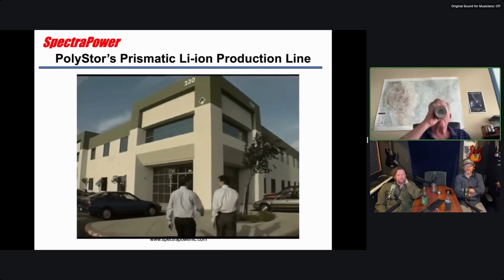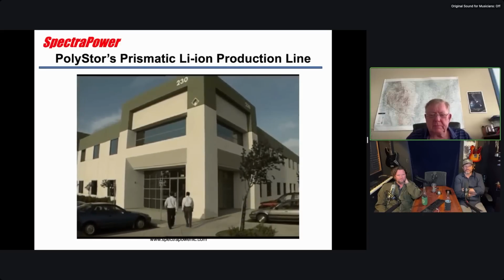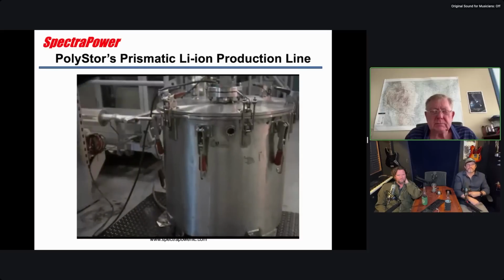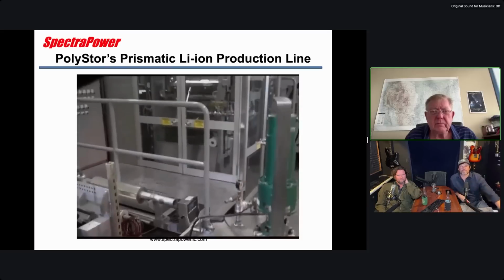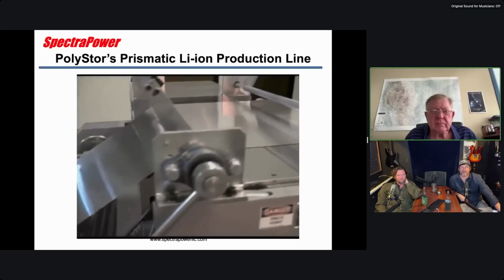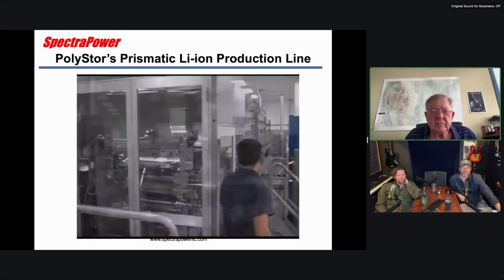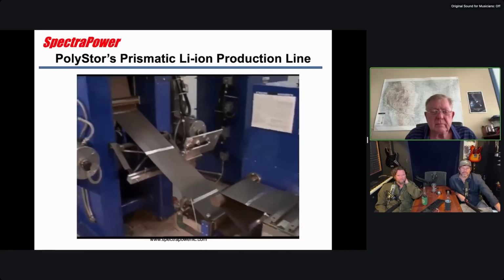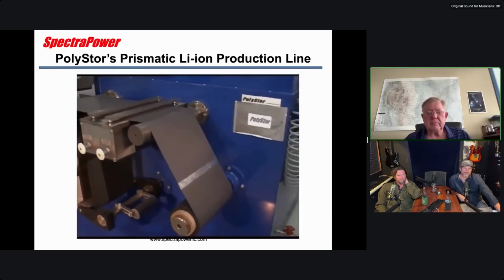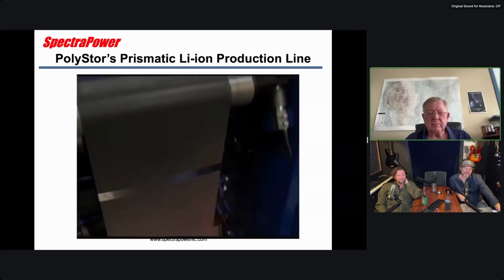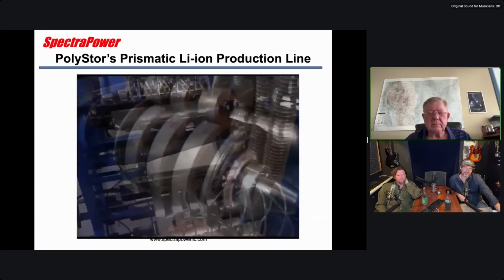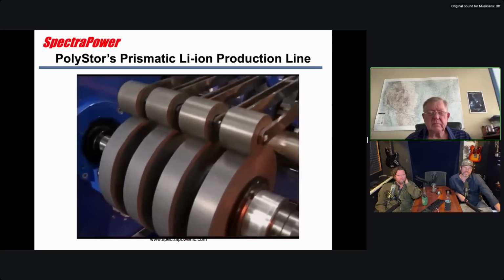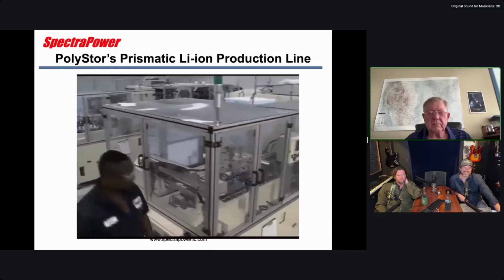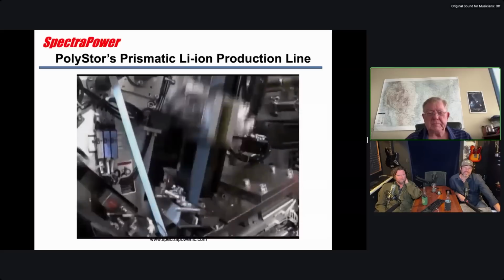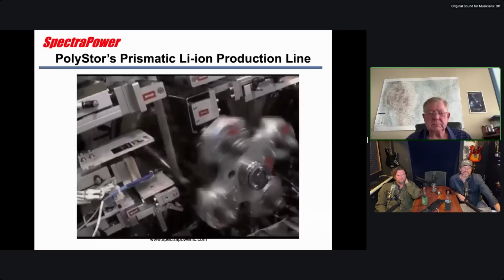Welcome to PolyStor's manufacturing facility in Livermore, California, just minutes north of Silicon Valley, the only one of its kind in North America. PolyStor is the first in the world to use high-capacity lithium nickel cobalt. High-volume roll-to-roll coating equipment mass produces the electrode material at high yields with low costs. Electrodes are coated and compressed for maximum packing density. A slitter cuts the electrode materials to exact dimensions. The electrode materials are now ready for the assembly line. Using state-of-the-art winding equipment, the positive and negative electrodes are wound into a core.